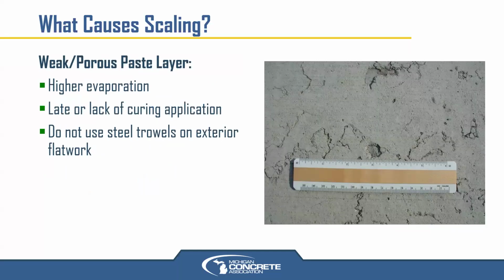All right, what else can cause scaling? A weak or porous paste layer because of high evaporation. The cement particles don't have the water nearby them because it had evaporated, and that cement powder is just wasted and it's just sitting there, and it is a void then. If it's a grain of unhydrated cement in the surface, it has zero strength. And that's typically due to late or lack of curing application and high evaporation rates, or a combination of something in between, as well as steel trowels on exterior flatwork weakening that surface paste layer, even if it's properly cured after that finishing operation.